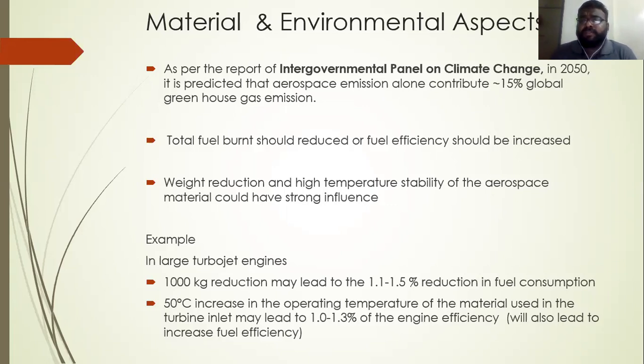For example, a 1000 kg weight reduction may lead to a 1.1 to 1.5 percent reduction in fuel consumption. Just imagine. So weight reduction plays a major role. Similarly, by increasing the operating temperature of the current alloy in use by just 50 degrees C, we may increase engine efficiency by 1.0 to 1.3 percent. So the main tool to reduce this environmental effect is reducing the weight as well as increasing the efficiency. Increasing the efficiency can be directly contributed by increasing the operating temperature of the material. So this is how the material and environmental aspects are correlated.